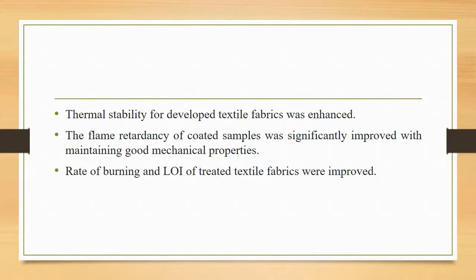Rate of burning and LOI of treated textile fabrics were improved, achieving 0 mm per minute and 24.3 respectively, compared to the high flammability of the untreated sample. Hydrophobic properties of treated textile surface were enhanced, achieving a 145-degree water contact angle. Flame retardancy and action of the developed textile was investigated and discussed.